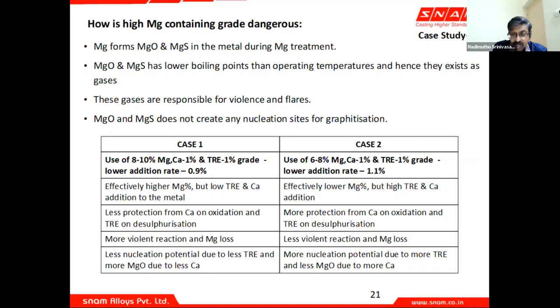it is going to be lost. So buying a higher grade of magnesium, ultimately that magnesium is not going to serve the purpose for anyone, because it is going to burn away or it is going to result in a flare and it is going to be lost. So ultimately we will be increasing the entropy of the universe, or the ecosystem of the foundry. So use of 8 to 10% gives you effectively higher magnesium, but it gives less protection from calcium on oxidation. It's more violent and less nucleation potential.